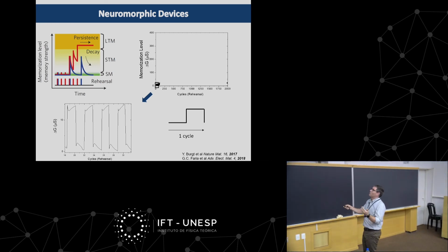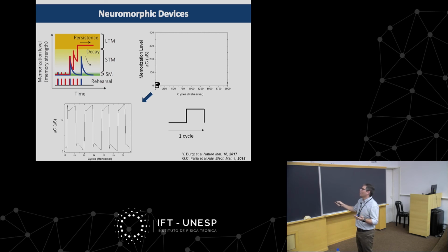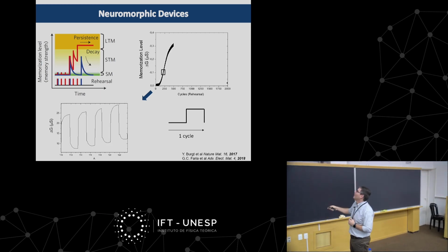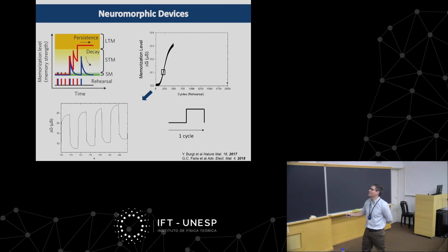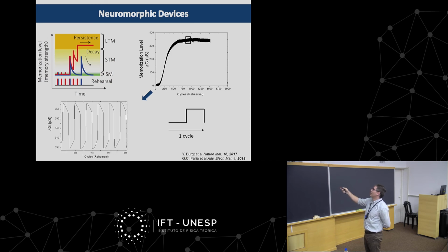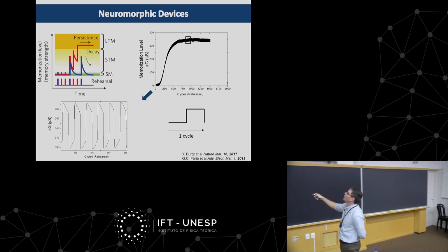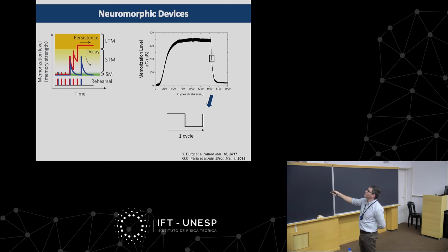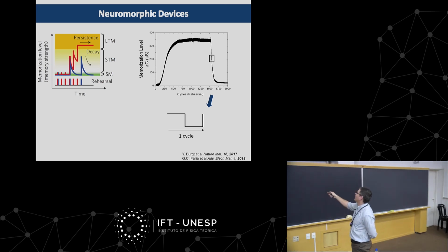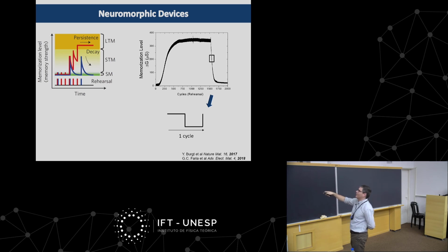So, with that device, what we wanted to do is basically replicate this multi-memory brain model, and what we did is open and close for very different numbers of cycles. Here it is from 0 to 2,000. And you see that from 0 to less than 200, it stays more or less constant, which is basically the short-term memory. And as I go up, this starts changing conductivity. As you can see here, it starts going up, very similar to the model published by Atkinson, and keeps going up with rehearsal to the point that it gets to a taper, or the plateau level, which is basically the persistent memory. And of course, because this is an engineered machine, I can apply a reversal of rehearsing, so I can erase that memory and bring that memory down. So you can basically see that, using that structure, I could replicate the brain's multi-memory model.